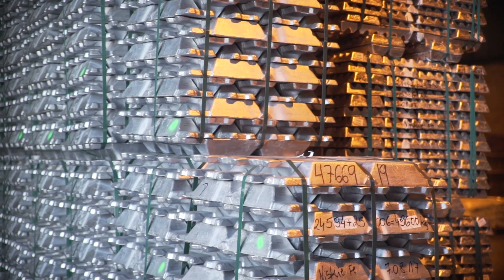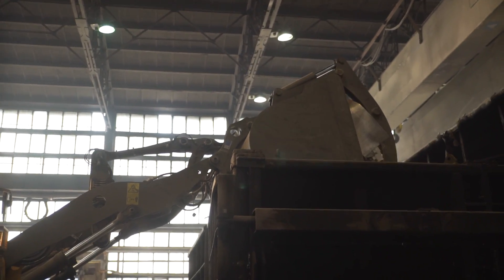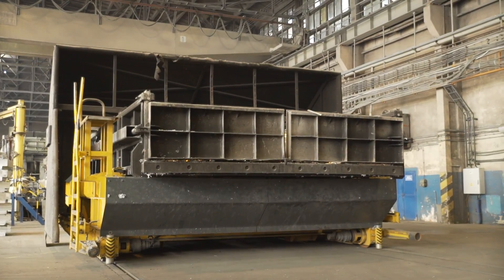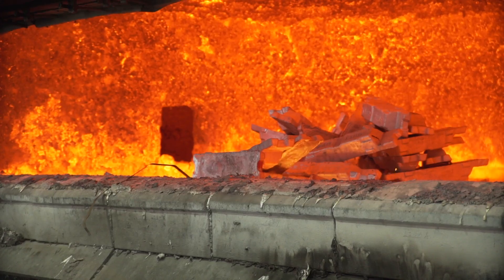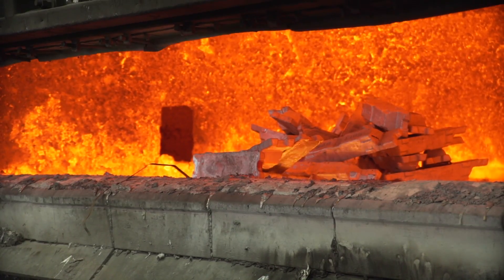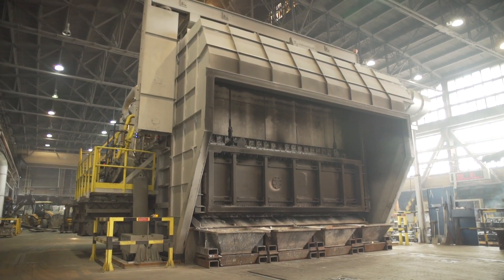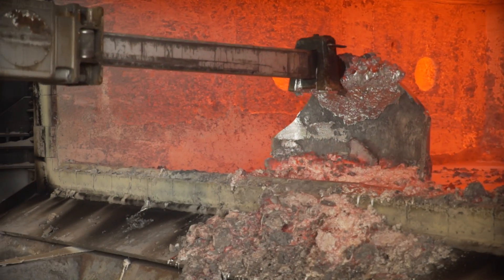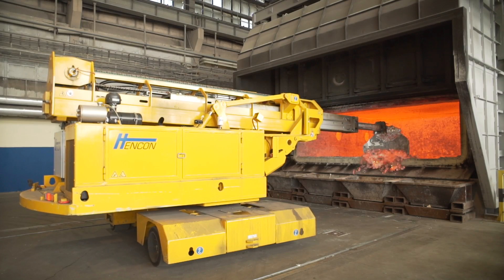Different types of alloying additions are used for correcting chemical composition. The metal is loaded onto the charging machine, which transports the charge directly to the melting gas-fired furnace. This is where the re-melting process is conducted, at temperatures up to 1000 degrees Celsius. During melting, the dross arises — that is oxidised metal which has to be removed from the furnace.